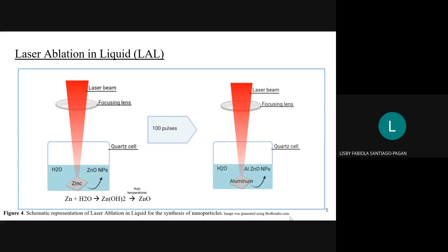In the present study, the solid surface was a zinc metal target, and the laser beam was pulsed with enough energy to release the zinc particles into the aqueous environment. This ablated zinc reacts with water molecules to then produce the zinc oxide nanoparticles.